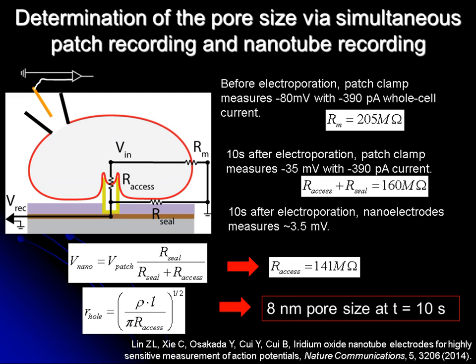So one of the questions we were repeatedly asked is exactly how large is the pore size through electroporation. If the electroporation creates a very large pore, it can easily kill the cell. So what we did is we found the cell sitting on top of the nanotube, and then we used patch clamp to patch on the same cell.